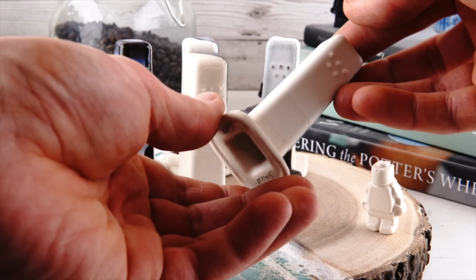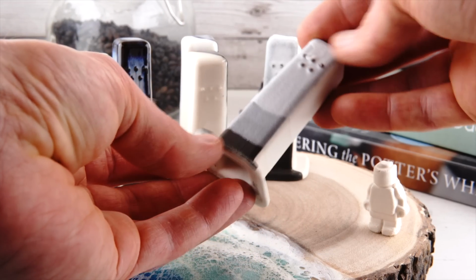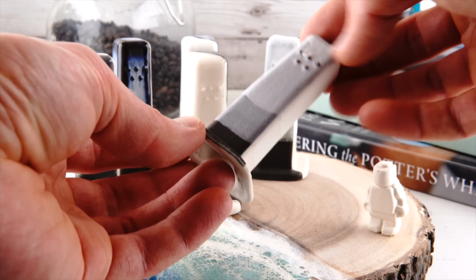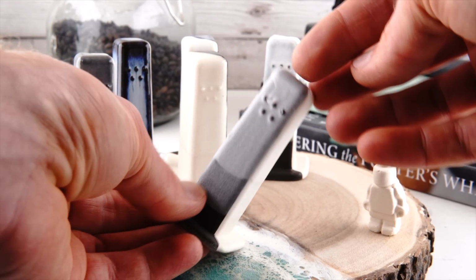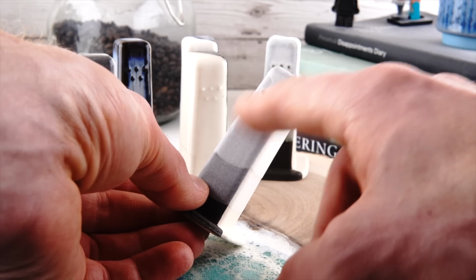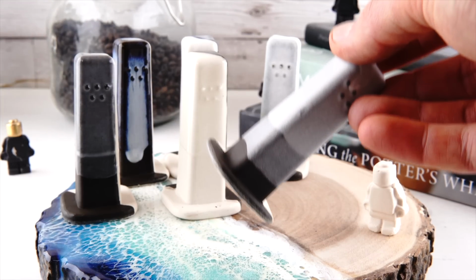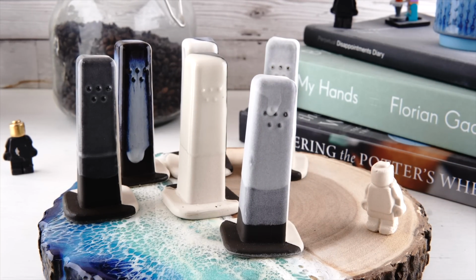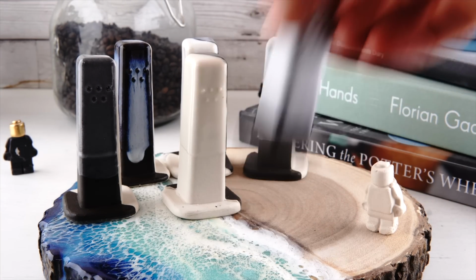And the one with loads of silica, also completely underfired. You can see the drips preserved from the application, where if it had melted that would have flowed down into it. It's matte, but it's not matte because of the underlying chemistry. It's matte because it's underfired.